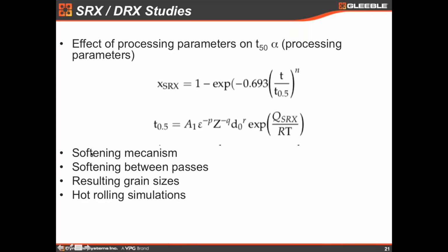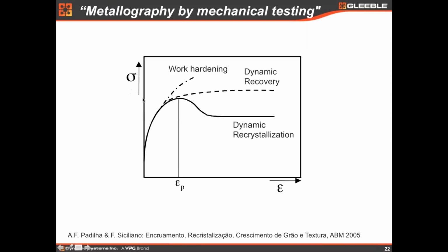So at the Gleeble, we can understand which softening mechanism is operating. We can measure the softening between passes. We can see the resulting grain sizes, and also we can perform hot rolling simulations. So first, which mechanism is operating? We see in a simple stress strain curve at high temperature, at a very high strain, that there's a work hardening curve, there's a dynamic recovery curve, and it gets a flat plateau here because there is no grain boundary movement, so there is no massive elimination of dislocations due to recovery. Recovery is a slow process.